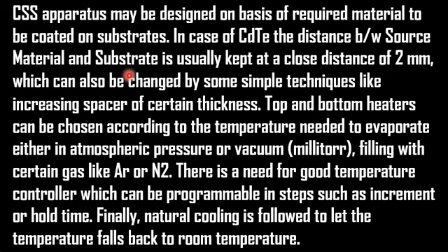Usually for cadmium telluride, the precursor material, which is basically cadmium telluride in the form of powder or chunks, and the substrate are kept around 2 millimeter apart.